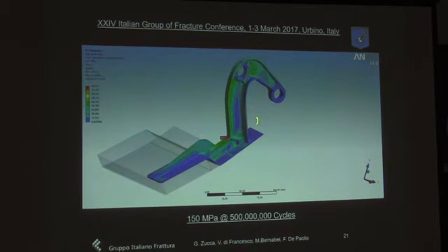So what we find is that a stress concentration point exists, but is far from the fracture initiation. The fracture initiation is here, and the concentration point, the tension point, is here. And also its value is very slightly above the fatigue limit for this aluminium. And this is a simulation performed with a safety factor of 1.5 applied to the normal load acting on the piece.